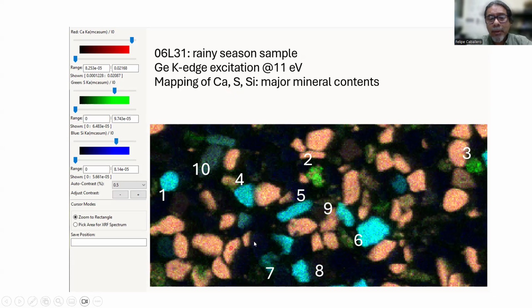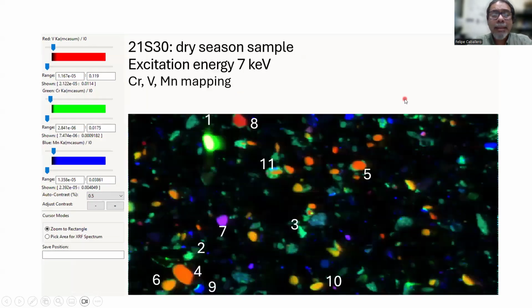So you can see here the different pebbles, and the color that is associated with calcium in red, sulfur in green, or silicon in blue. And so we select these particular particles to be analyzed for chromium and manganese. In the case of this other sample, we perform the same mapping of calcium, silicon, and sulfur. And particularly here, we are showing the chromium, vanadium, and manganese mapping. You see, this is a very rich chromium particle. This number 7 is mixed between manganese and vanadium, and so on. For example, number 9 is very rich in manganese.